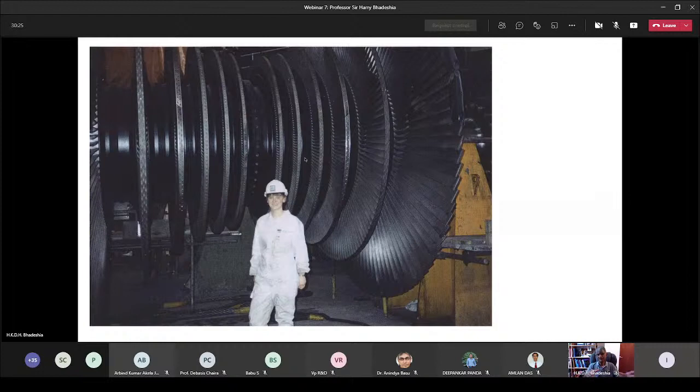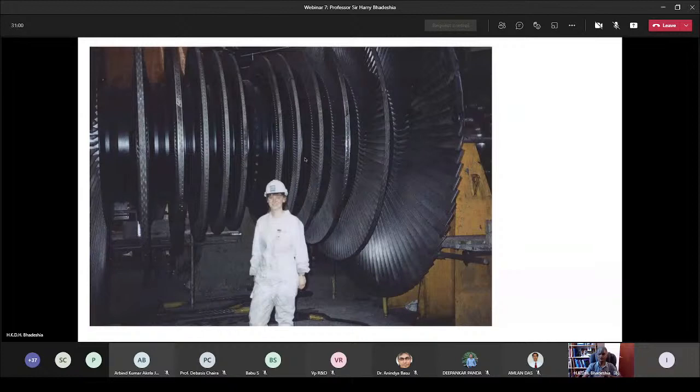You have to generate the right structure by continuous cooling. And bainite can form at relatively slow cooling rates, which is why, for example, the steam rotor is made from 2¼ chrome 1 moly steel, which transforms through the section into a bainitic microstructure. So the advantage of bainite is that you do not need to cool rapidly. You don't set up stress gradients in your large component, and you get a relatively uniform microstructure in your whole component. So let me now briefly explain the microstructure that we call bainite.